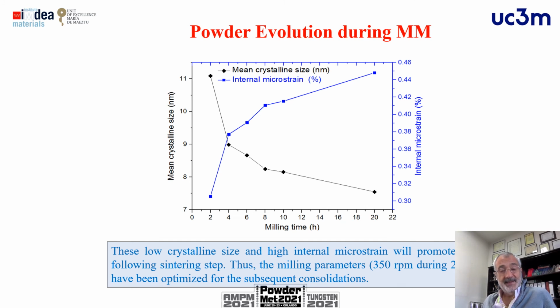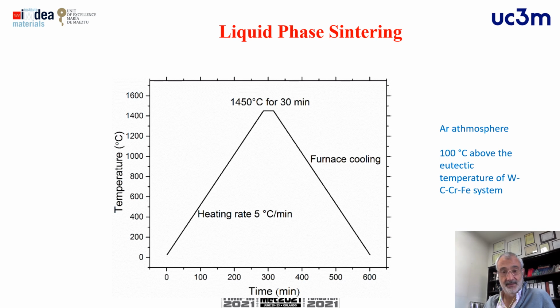So with the mechanical milling, we usually have this effect that we increase the internal microstrain and we strongly reduce the crystalline size. Reaching this small crystalline size, we can expect to have at the end this so-called nano size cemented carbides that we are looking for, in order not to reduce too much the fracture toughness while increasing the hardness. We have prepared some bulk materials through liquid phase sintering with these conditions.